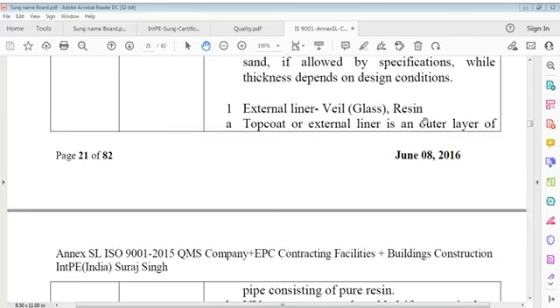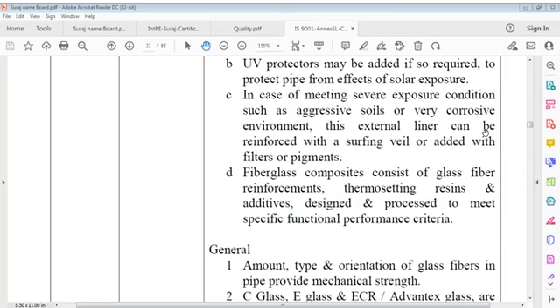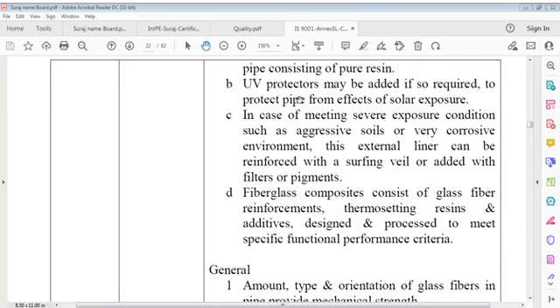External liner, resin: the top coat or external liner is the outer layer of the pipe consisting of pure resin. UV (ultraviolet) protectors may be added if required to protect the pipe from the effect of solar exposure. In case of severe exposure conditions such as aggressive soil or a very corrosive environment, this external liner can be reinforced with a surfacing veil or added with fillers or pigments. Fiberglass composites consist of glass fiber reinforcement, thermosetting resins, and additives designed and processed to meet specific functional performance criteria.